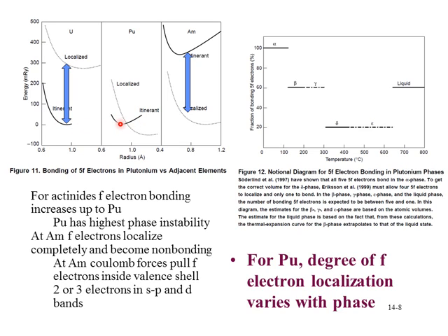Over here we get a mixture of going from delocalized to localized, where in americium the f electrons are more localized. And then here's fundamentally the fraction of 5f electrons involved in bonding. As we see, we start off with the alpha phase. As we would see here, we have the largest amount of actinide behavior, so the f electrons are involved in bonding. We get a decrease as we go down, to the least dense phases, which have the lowest amount of f electron contribution in the metal bonding, and we actually go up when we hit the liquid phase.